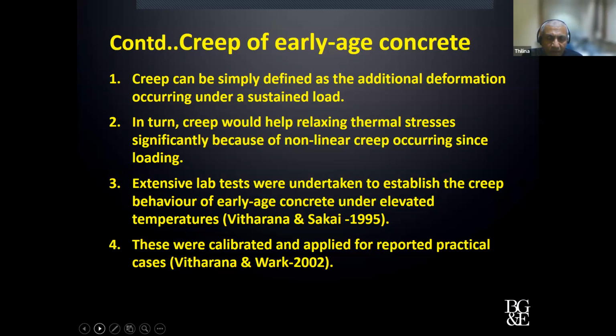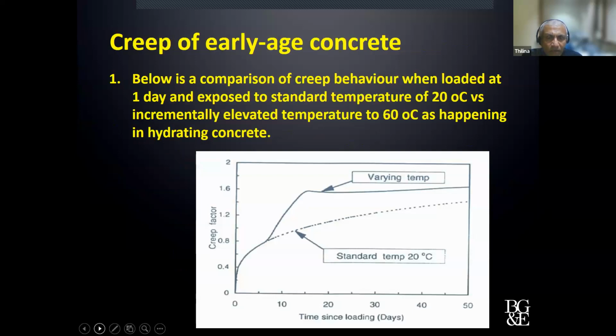There are a lot of early age creep models now, but we also did one in 1995. It takes both the temperature and the time into account at early age. Because at early age creep should be high, because it is still hardening. It's like a paste. Next one, please. Yeah, this example. The bottom one is a standard creep test done at 20 degrees and 80% humidity. The top one is the same concrete mix at varying temperature up to 60 degrees. The creep factor is about 1.6. It's basically increased by about 160%. Next one, please.